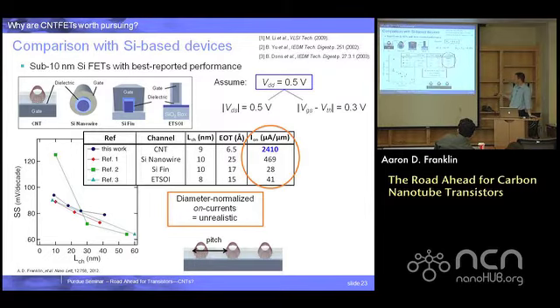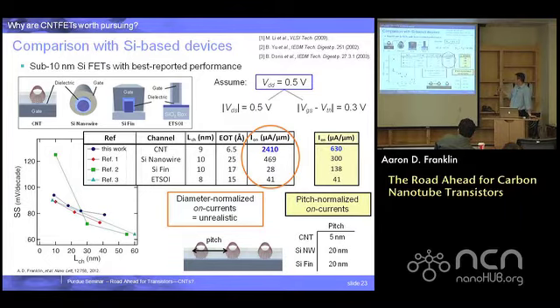So it's more fair to look at a pitch normalized current. And these nanowire guys were just as bad, by the way. They reported diameter normalized in their paper, so shame on them. Because you're never going to put silicon nanowires right next to each other. You have to get a gate in there, right? So we modified this for a pitch normalized.